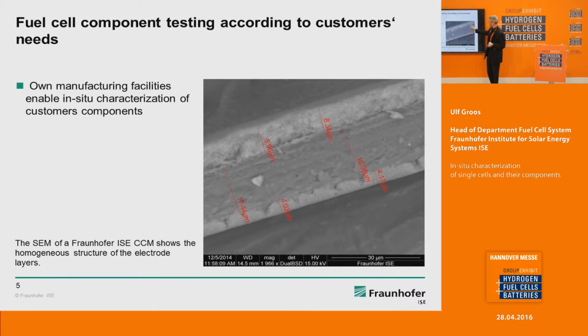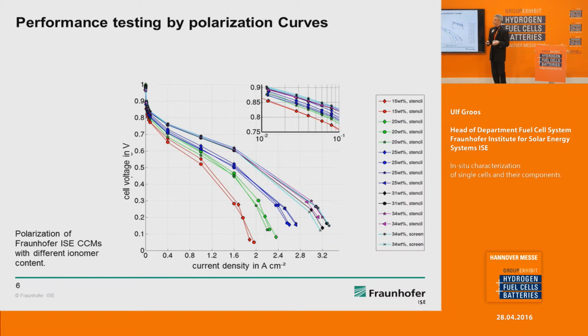What you see here is an SEM picture of a CCM which we made, and we see a very homogeneous structure. A homogeneous structure is one point, but performance is the other point. In this graph, you see a variation of the ionomer content indicated by the different colors. We changed the ionomer content within an electrode, and then we made polarization curves. We produced several samples of the MEAs, and we see that for each sample, the polarization curves are matching. So this again shows that our manufacturing method gives reproducible results.